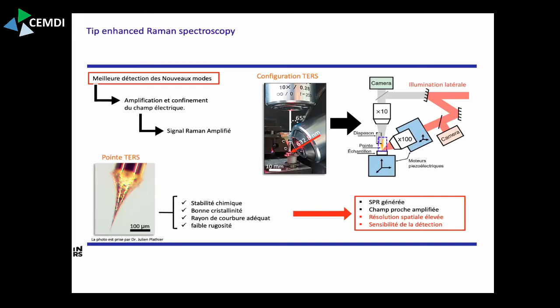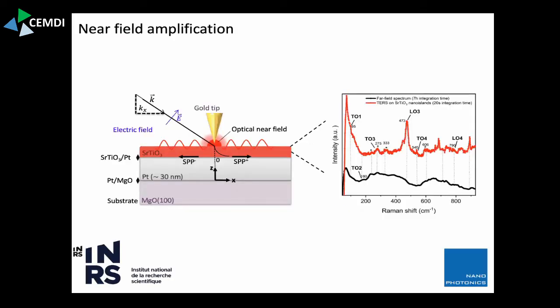So this is optical imaging, which in principle would allow us to measure along the steps. Now, we're not quite there, but I'll show you some interesting results because it didn't go the way we expected at all. So this is the configuration. We have the strontium titanate surface on platinum. It's not at all as flat as we want you to believe it here.